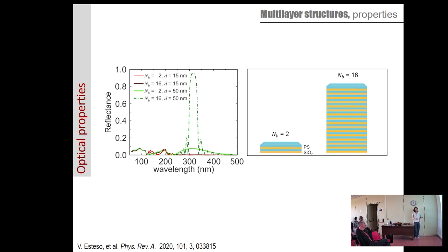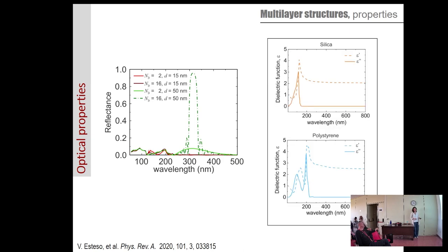So we did this analysis of the reflectance response as a function of the wavelength for thin and thick films, for 2 and 16 bilayers, and a bilayer is silica and polystyrene, something like these two skins. And here we can observe, for the case of the thick films, the Bragg peak, whereas here, where the Bragg peak for thin films should appear, nothing happens. This is related to the fact that both silica and polystyrene absorb a lot in that spectral range where we should expect to have the Bragg peak.